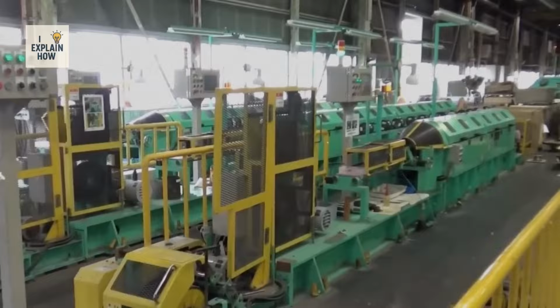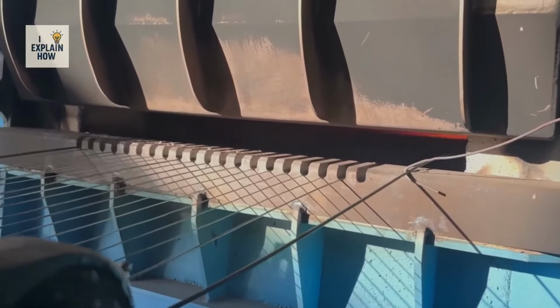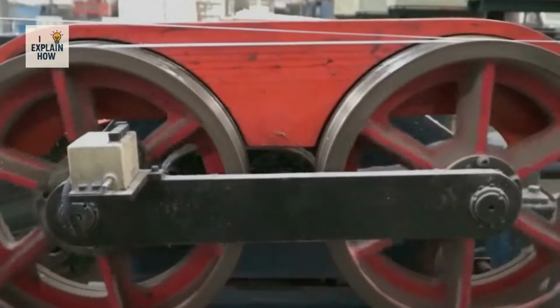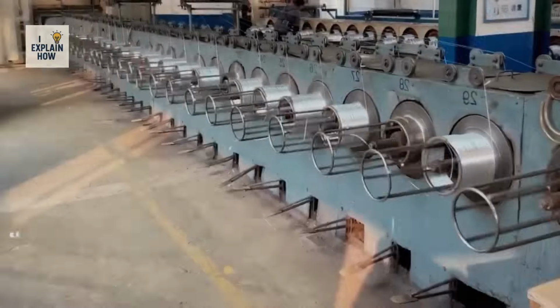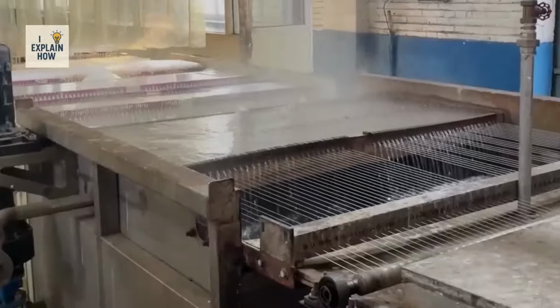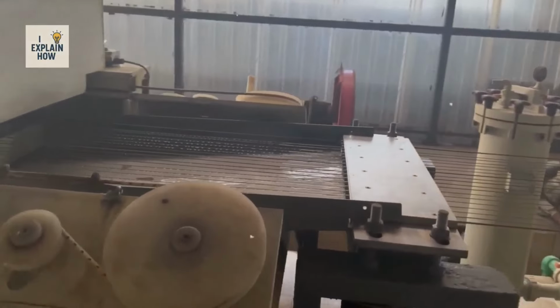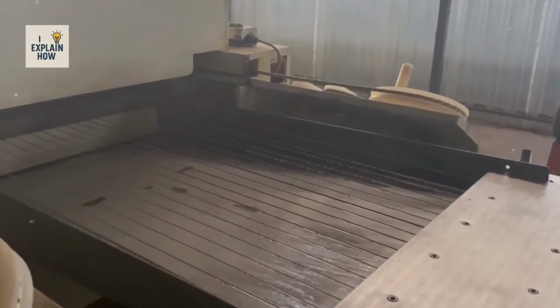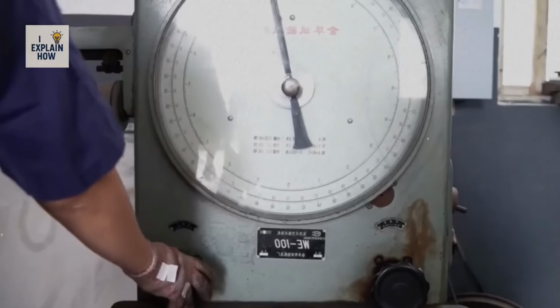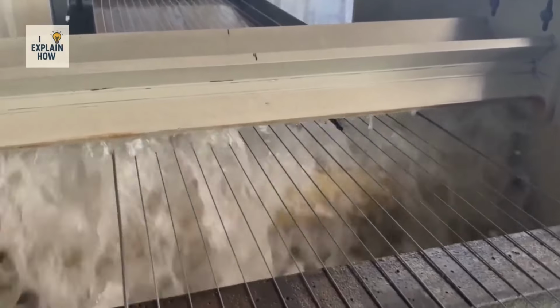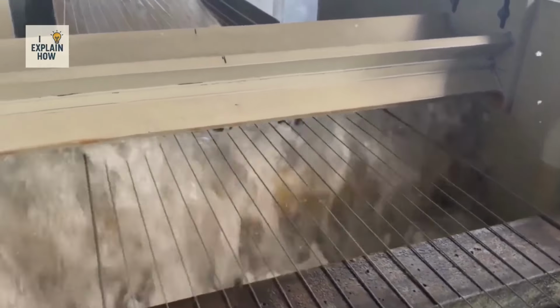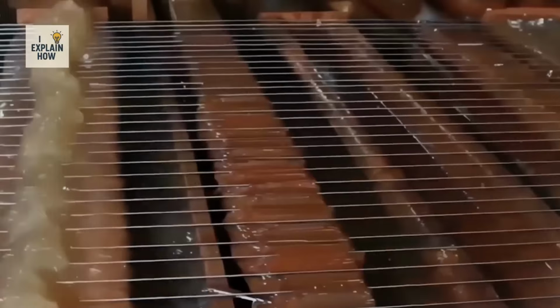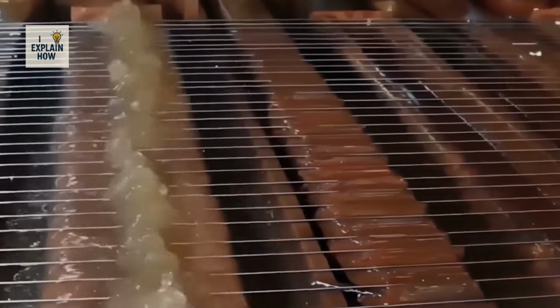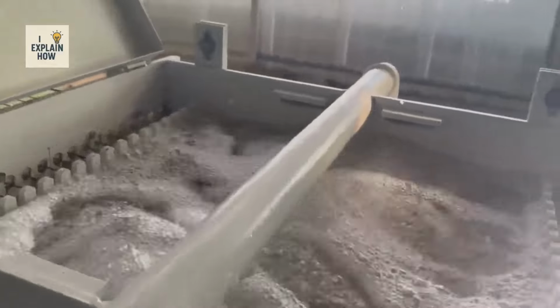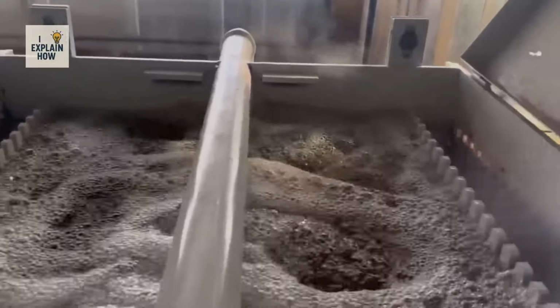Next comes the anti-corrosion coating. Depending on its final use, each wire receives a protective layer, usually zinc or polymer. Exposed to moisture, salt water, or chemicals, this invisible shield prevents oxidation. Before being coated, the wire is carefully cleaned with a mild acid solution to remove grease and rust. It is then dipped in a bath of molten zinc or coated with a polymer heated under controlled pressure.